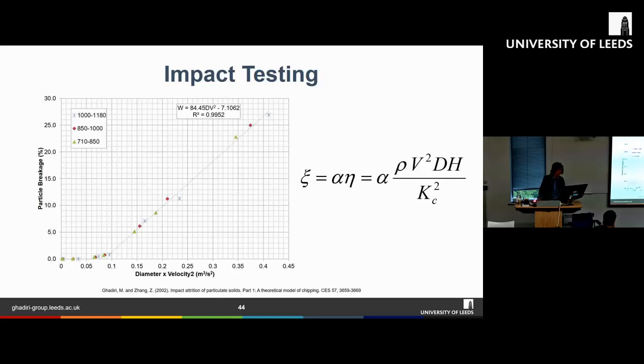So again, continuing looking at the same model, if we now plot particle breakage or fractional mass loss as a function of the particle size and velocity squared, we can get this linear relationship. And then a very interesting thing you can get here is this x-intercept. This is a very important and very useful parameter, as it signifies the transition point from no breakage to breakage. So using this, we can easily design different operations, telling us that if we have this particle size, what sort of minimum impact velocity is required for this size of particles to break.